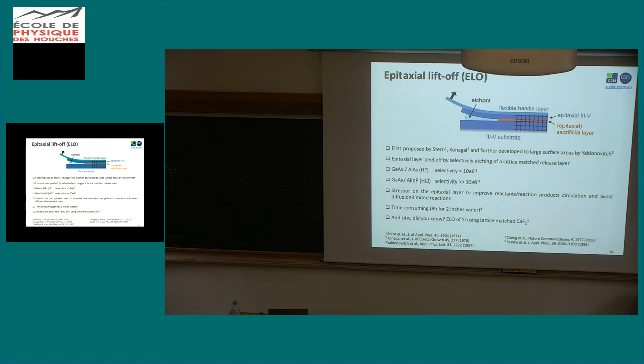So the epitaxial lift-off is this method to remove an epi layer of a III-V material out of a III-V substrate. It was proposed in the 70s, I believe, by Konagai and then improved by Yablonovitch. The idea is that you can grow, for example, on a gallium arsenide substrate, aluminium gallium arsenide, or just aluminium arsenide layer that is lattice matched. We saw it. And then again, your gallium arsenide epi layer, or directly your device, the entire solar cell. And then you rely on the fact that you have, for example, HF solution selectively etching only the aluminium gallium arsenide, leaving almost untouched the gallium arsenide. And if you apply some stress, you can manage to remove this layer.